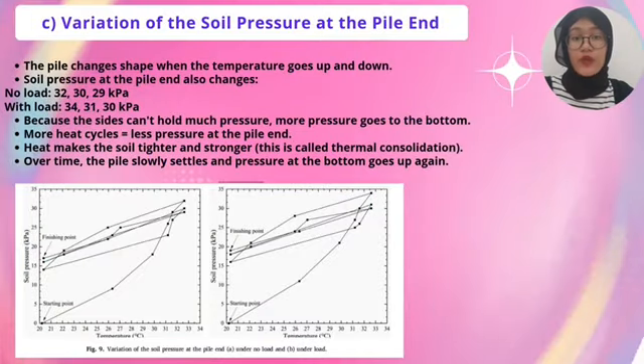Let's take a look at how soil pressure at the pile end changes as temperature changes. When the pile heats up or cools down, its shape slightly changes, and this affects the soil pressure at the very bottom. Without any load applied, the pressure ranged around 32, 30, and 29 kPa. But when a load was applied, the pressure increased slightly to around 34, 31, and 30 kPa. Why does this happen? Well, the side of the pile can't hold too much pressure, so a lot of it is transferred to the bottom. That's why we observe higher soil pressure at the pile end, especially under load.